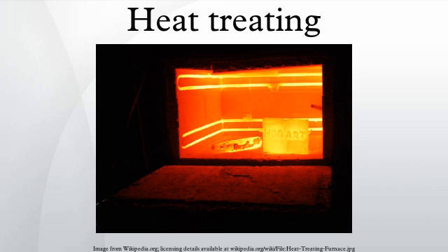Cold treating generally consists of cooling the steel to around -115 °F, but does not eliminate all of the austenite. Cryogenic treating usually consists of cooling to much lower temperatures, often in the range of -315 °F, to transform most of the austenite into martensite.